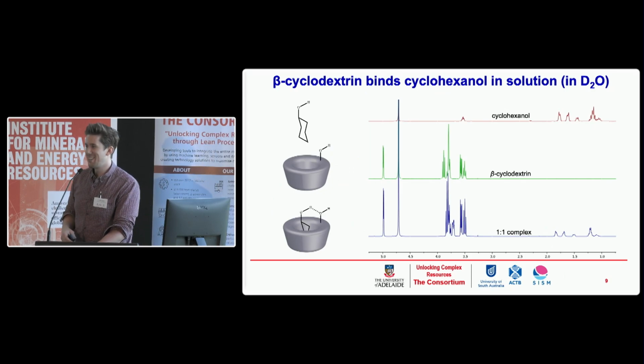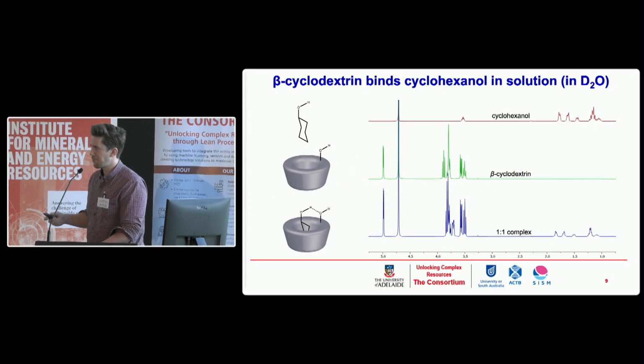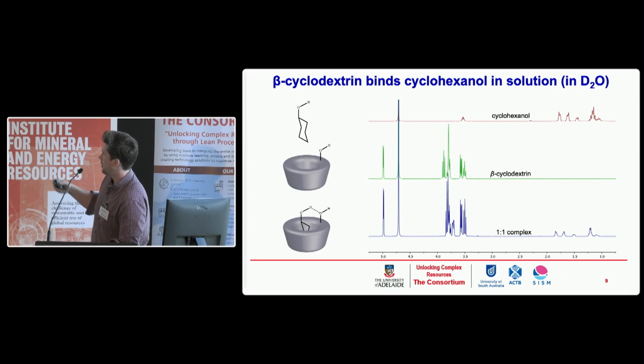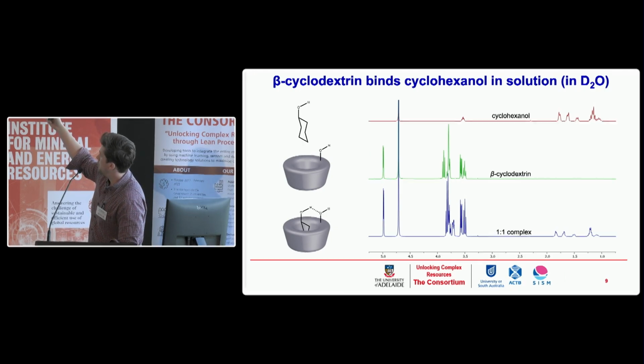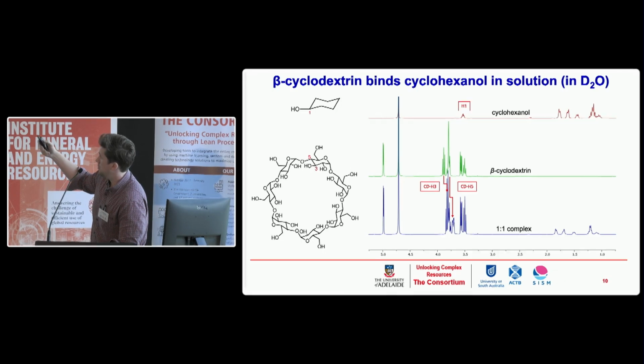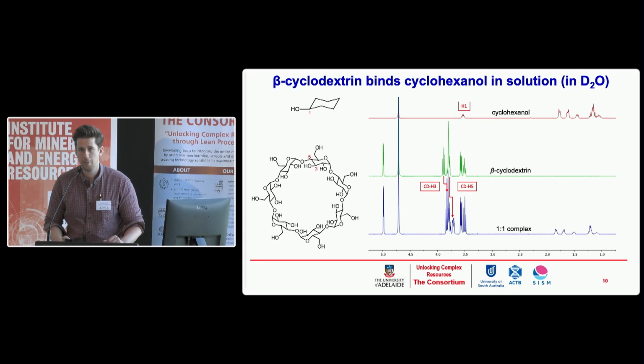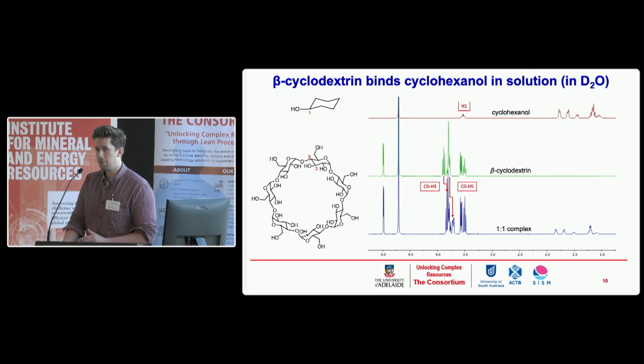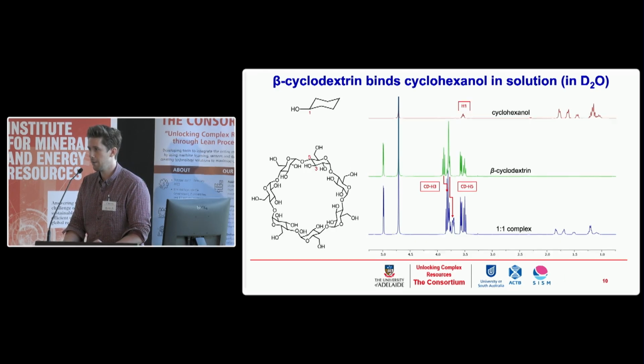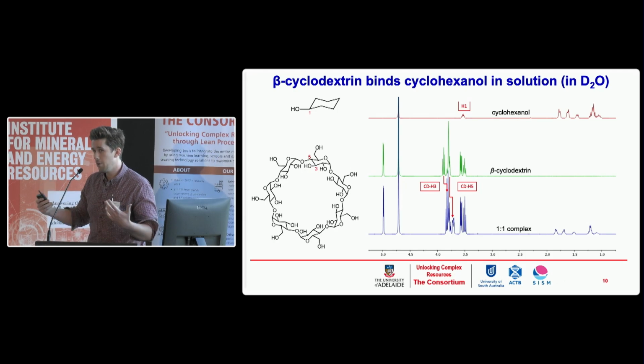So here's some nuclear magnetic resonance spectra of beta-cyclodextrin and cyclohexanol, and these are just to demonstrate the principle of binding. Basically, in the red trace, you have the protons relating to cyclohexanol. In the green, you have beta-cyclodextrin. And then when you mix them together in blue, you can see a shift in key resonances which correlate to the H3 and H5 protons of the sugars within the ring that make up the hydrophobic surface of beta-cyclodextrin. This is a means of confirming that you have complexation with your host molecule, your guest molecule within your host.